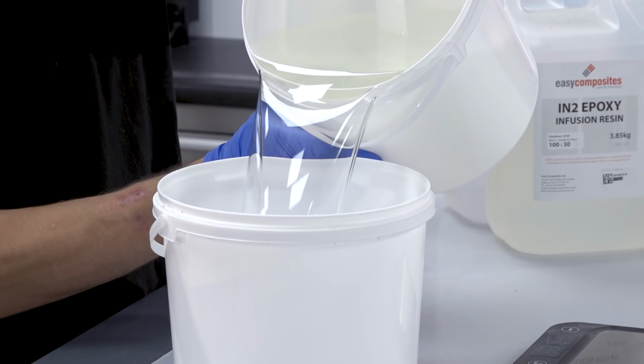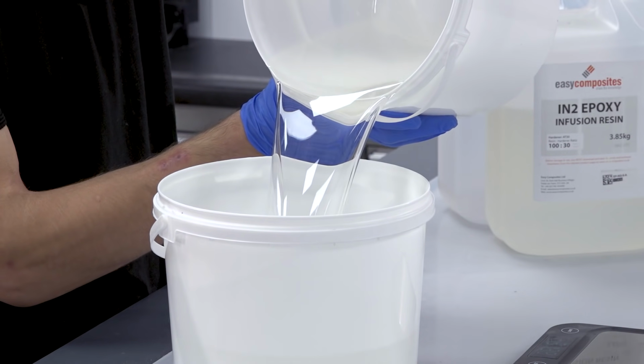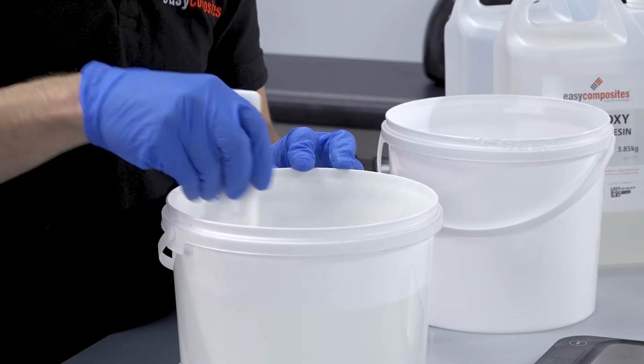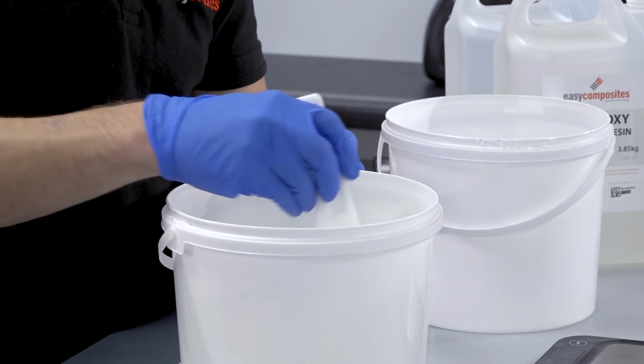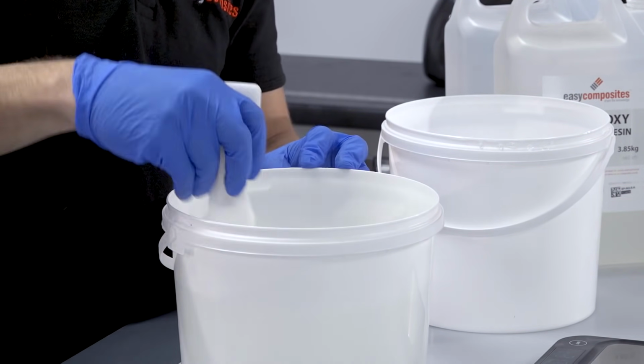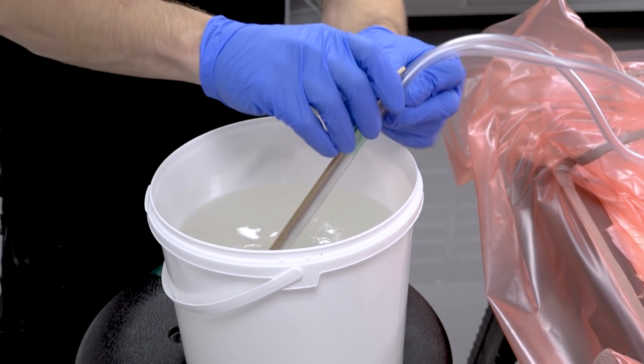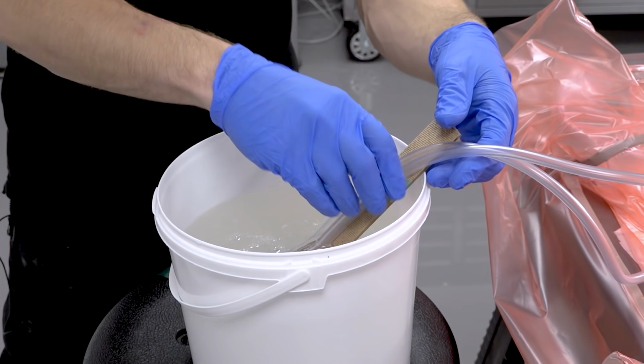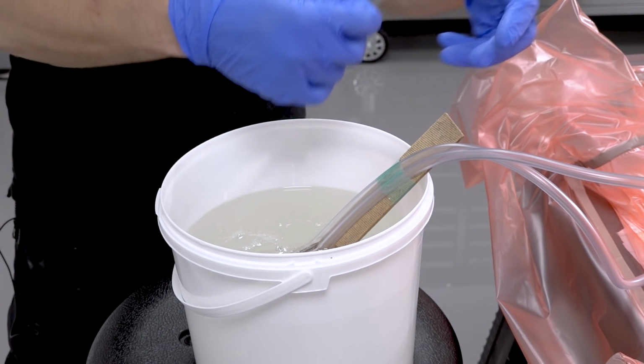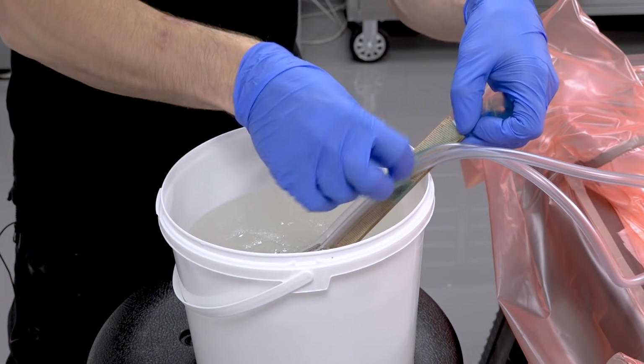Here I'm using the double pot method, so I'm pouring the mixed batch into a second bucket and then mixing again. This ensures that you will not have any unmixed resin trapped in the sides and bottom of the bucket. With the resin mixed, it's left to stand for a minute for the worst of the bubbles to escape, and the feed lines are then secured into the bucket with tape.